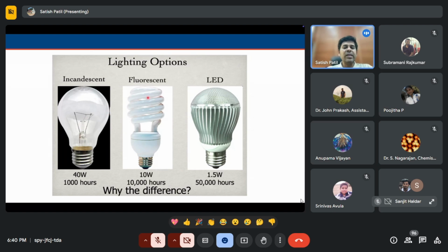whereas then to come over this, fluorescent lights were introduced, and now you see that instead of 40 watt, you have 10 watt, but the lifetime has improved to 10,000 hours. They work on the idea of a fluorescent, but these are again very toxic. It contains mercury in these lights.